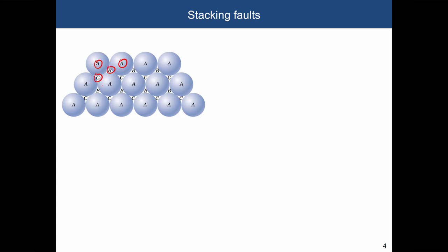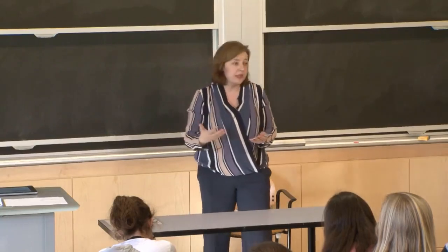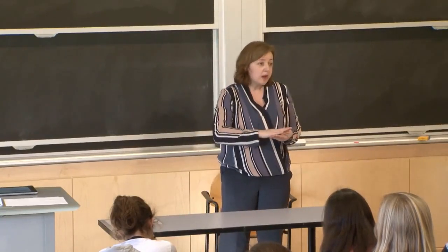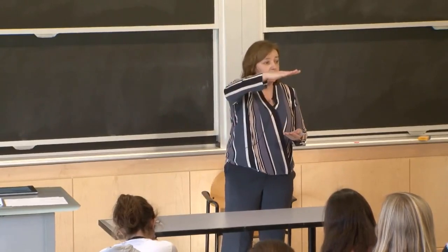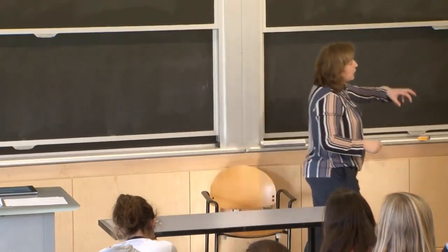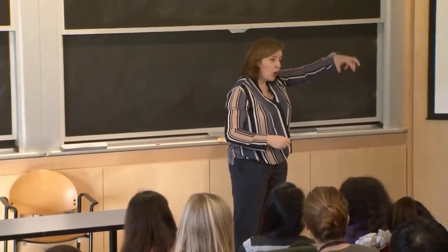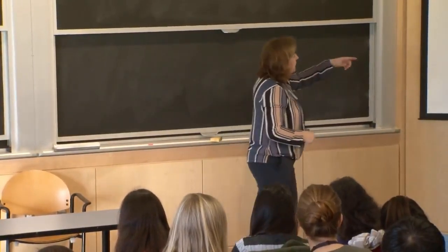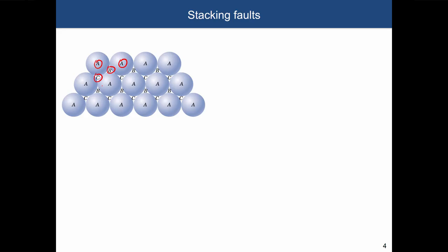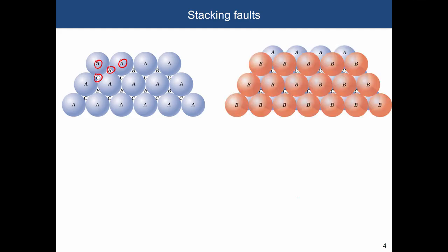So what you're doing is that you're growing, for example, the material, and you're stacking atoms on top of each other. So first you form one layer, which will form this close, dense packing structure. And then you're asking where the second layer will be, whether the atoms from the second layer will simply sit on top of the first atoms, whether they will take the position B or C, etc. And there is the major distinction between two classes of materials, which are FCC, in which the stacking is ABC, ABC, ABC.